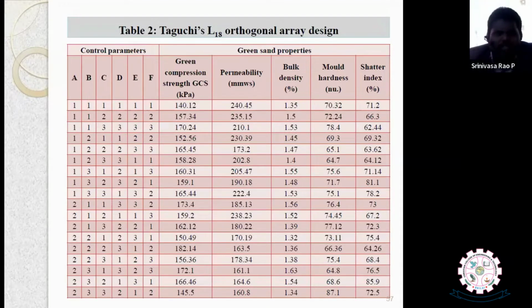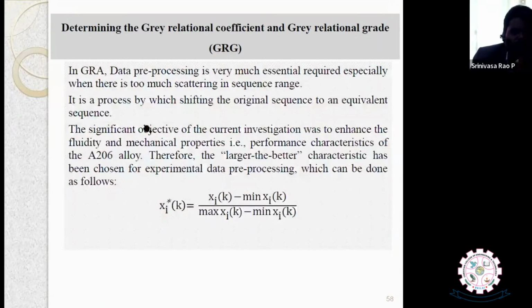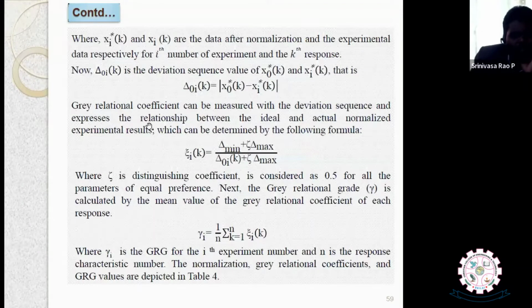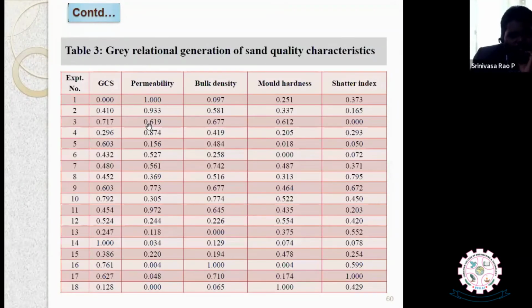We have used an L18 orthogonal array, and we found out the green compression strength, and these are the responses: green compression strength, permeability, bulk density, mold hardness, shatter index, etc. These are the various properties obtained by adding these materials at various levels. This is the procedure for the gray relational coefficient and gray relational grade. I don't need to explain all this procedure because it is a standard technique.